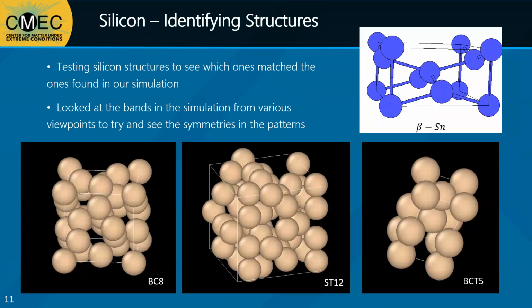We decided to try matching our shocked sample to known structures for silicon. Beta tin, seen here, is the expected equilibrium phase for these pressures, but there are metastable phases that exist, especially under the short timescales and kinetically inhibited conditions of shock compression. Some of the other phases that we tested against included the BC8 phase, the ST12 phase, the BCT5 phase, simple hexagonal, and simple cubic phases.